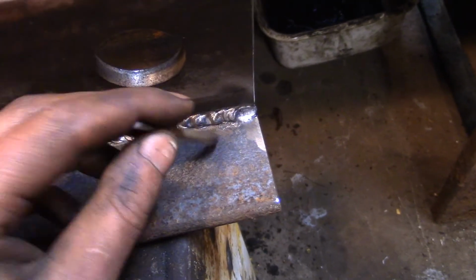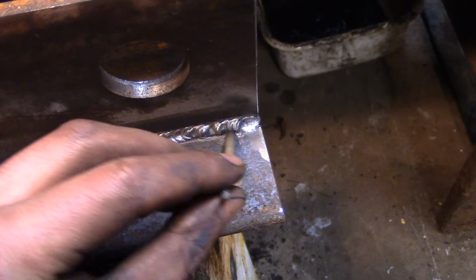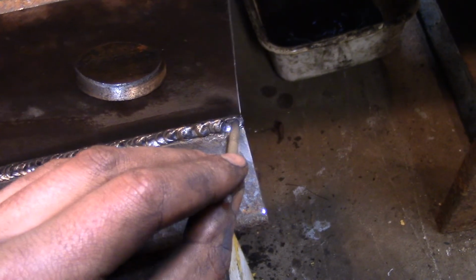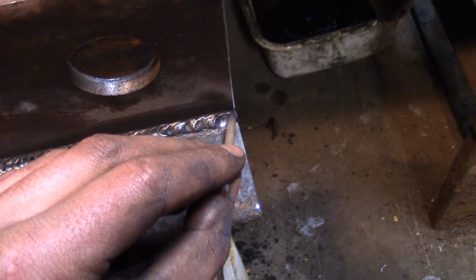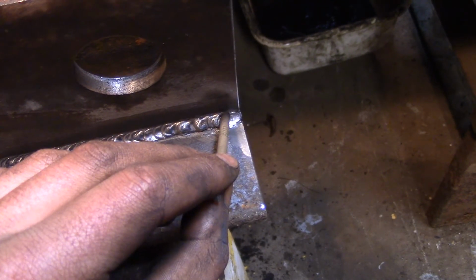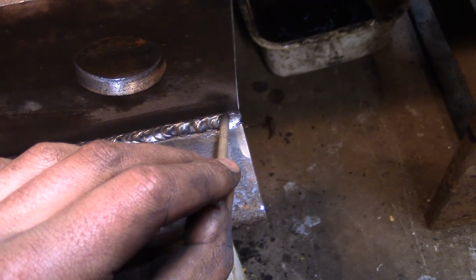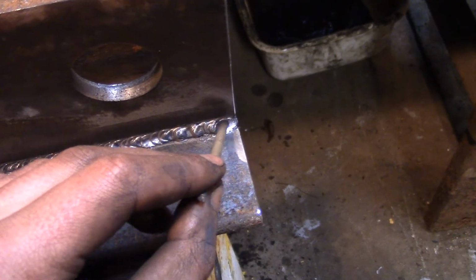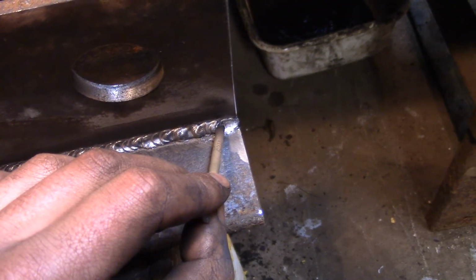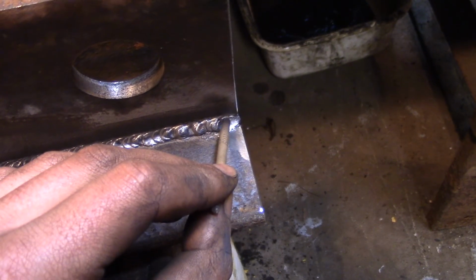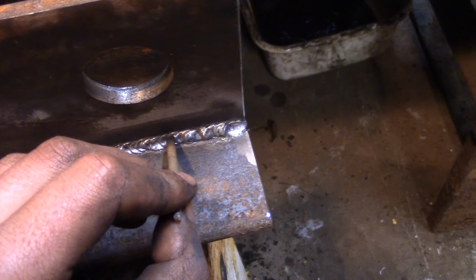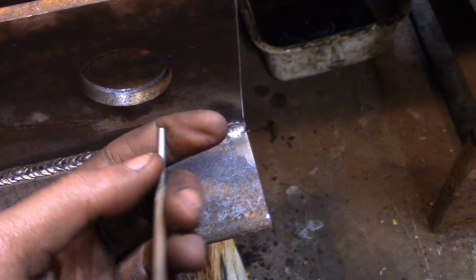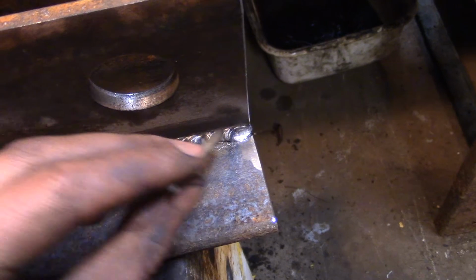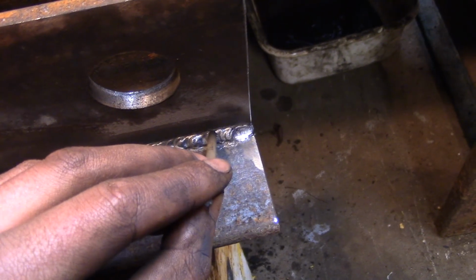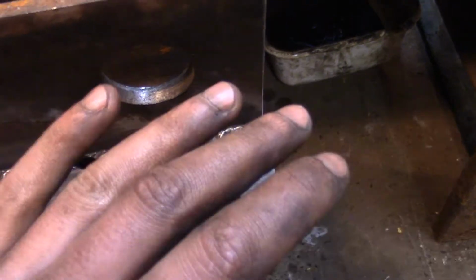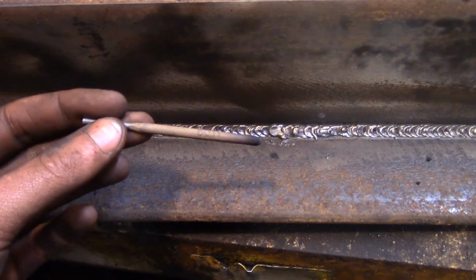And I struggled with that for a while until, again, Welding Tips and Tricks, he helped me out. You weld as normal, then once you get to the end of your weld bead, you backtrack maybe 1 or 2 rod diameters and hold it there for a second, and then you pull the arc away. Firstly, it pulls the heat away from the corner, and it allows the weld to puddle a little bit before you pull the rod away. Because if you just pull the rod away, you get a little crater and sometimes a little blowhole looking thing. But if you weld and then backtrack just a hair, hold it for a second and pull out, that stops.